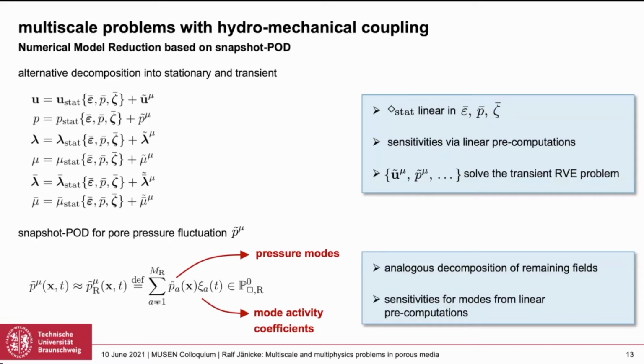So in practice, what happens is that we run, on the RVE level, training computations on this box with several loading cases. We extract snapshots, and those snapshots are the input data for the proper orthogonal decomposition, and basically it turns into solving an eigenvalue problem. The largest eigenvalues correspond to the dominant pressure modes. Then we truncate after a few of them, and typically one can show that really few modes are sufficient to contain all the relevant information. And that's why it becomes way cheaper.